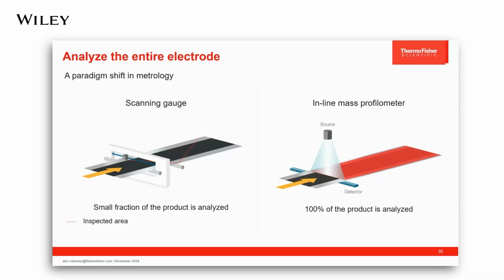A scanning gauge usually consists of a frame on which the sensor moves from one side of the electrode foil to the other and repeats. The resulting dataset captures a zigzag pattern across the electrode as the coated foil moves through the process. For example, if the line speed is 60 meters per minute and the sensor takes 5 seconds to move left to right, 5 meters of product would have passed until one profile measurement is complete. Areas that do not pass under the sensor are not analyzed, and coating variations or defects could be missed.